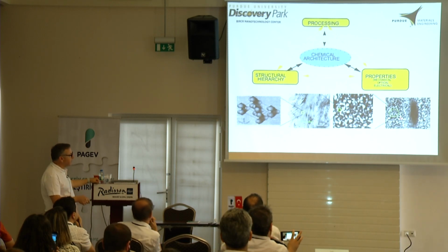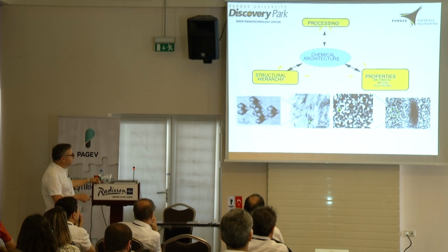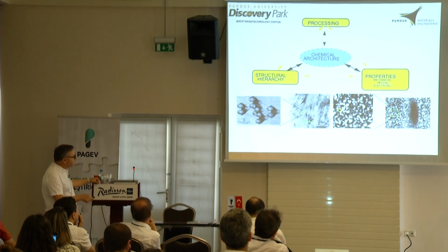Here's an example of hierarchy. This is an injection molded polypropylene, microtomed, and if you keep on zooming, you eventually get to the polymer chain level. This is called hierarchy, so you really need to understand the whole hierarchy. This is a spherulitic structure. This is the shear-oriented layer. And here are the spherulites, and spherulites are made up of lamellae. These are small crystals. And then this is basically the unit cell of polyethylene, not polypropylene. So you have this hierarchy.